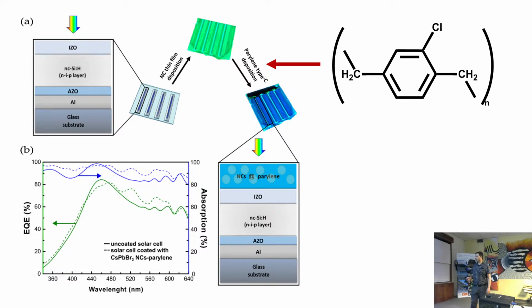And so our first test was to use nanocrystalline silicon photovoltaic cells. We covered this with the quantum dots, and by vapor deposition, we deposited this polymer to stabilize the quantum dots above the photovoltaic cells. And then we could make comparisons between uncovered and covered photovoltaic cell. So this, for instance, is the photovoltaic cell without the quantum dots, and this is the photovoltaic cell with the quantum dots. Immediately see light absorption in this area increases, and the efficiency has an incremental improvement in this region. And in this region also there is an incremental improvement. It's not huge, but it is promising.